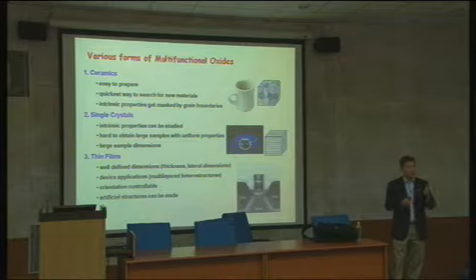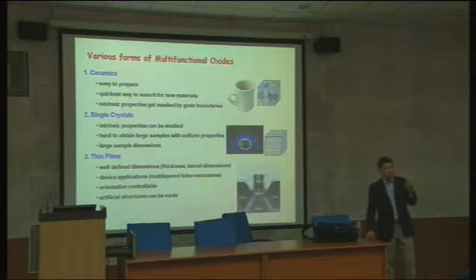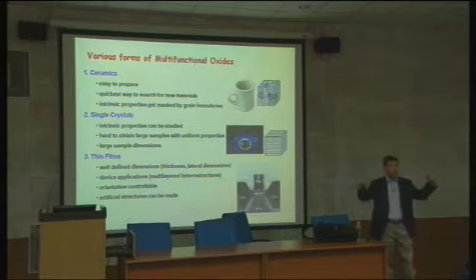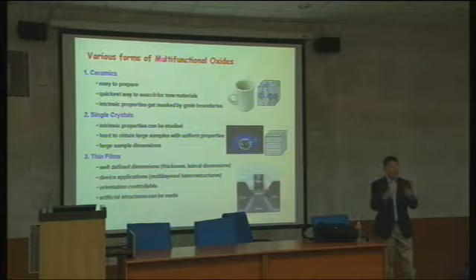But when you grow large crystals, sometimes oxygen diffusion over a large distance is very, very slow. The solid-state diffusion is very slow. In the surface region the oxygen stoichiometry is good, but inside it is oxygen deficient. So that's one of the problems of making large single crystal materials.